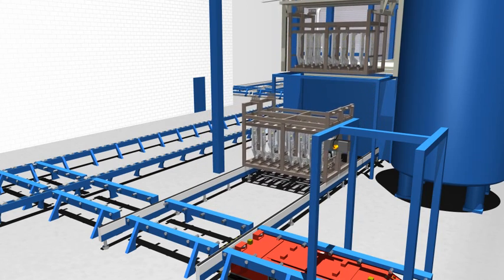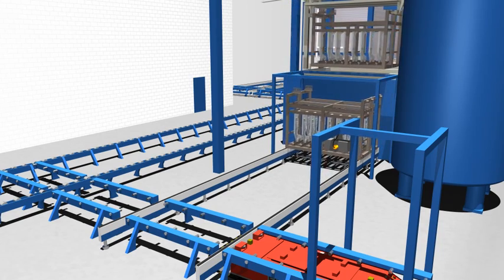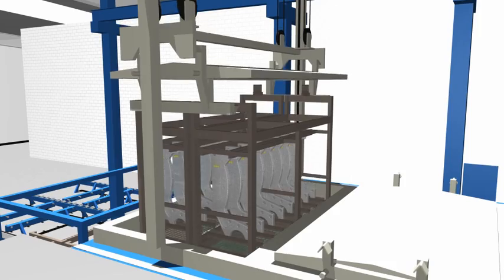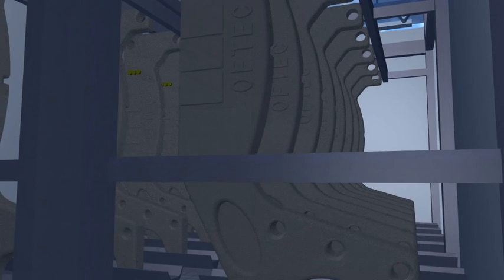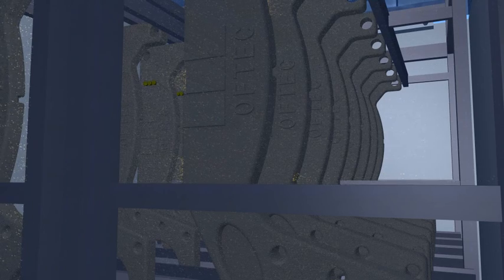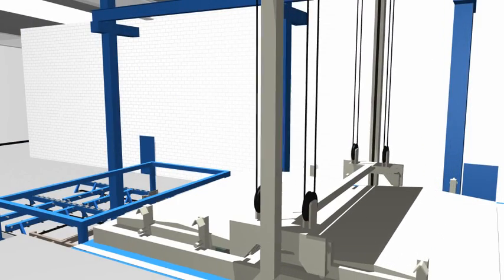In order to guarantee that the repeat quality of the coating remains at the highest level at all times, the parts have to be pre-treated in various basins. With an automatically controlled loading device, the basket is transported to the first basin, the immersion degreasing basin. This process consists of several basins needed to degrease the parts and reduce alkalinity. When the parts are immersed, grease and dirt particles dissolve at a temperature of approximately 70 degrees Celsius. These particles are filtered from the basin continuously, and the recycled liquid is reintroduced into the basin, which leads to a continuous medium cycle.